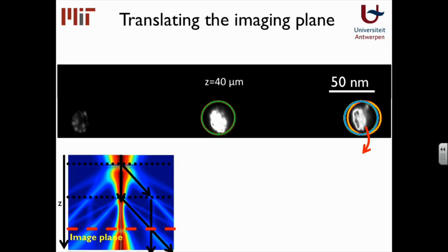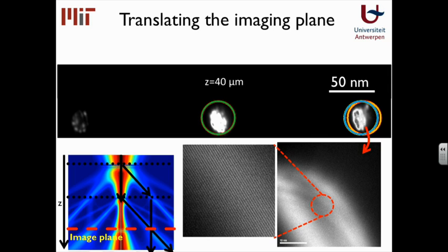As we continue moving down, the two beams eventually merge with each other, and we can take a high resolution image of this merged spot, zoom in a bit more, and finally we see very well resolved interference fringes, and the period of these fringes is about 3.2 angstroms, which is what we would expect to see from interference between 000 and 111 silicon diffracted beams.